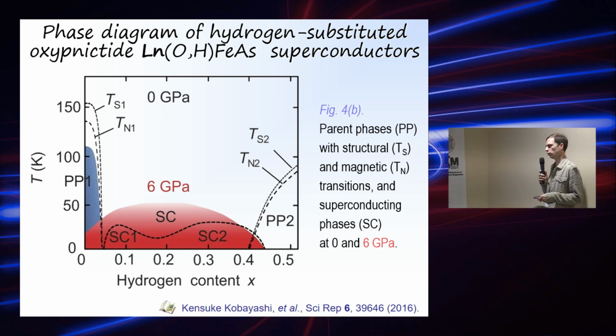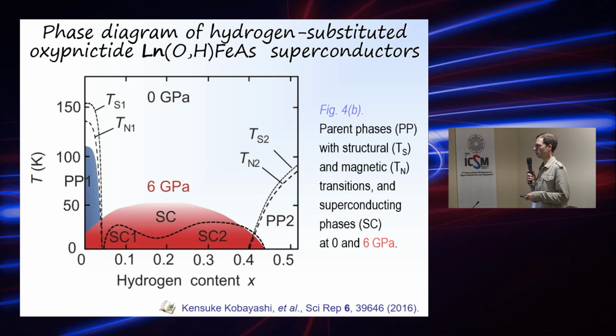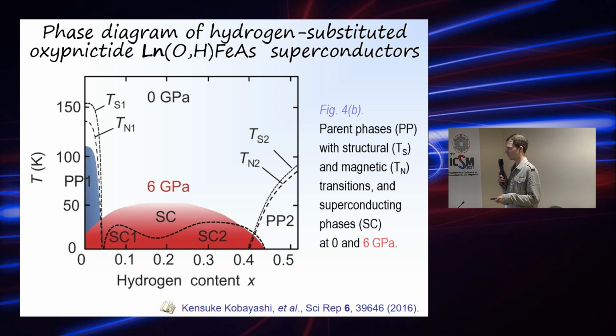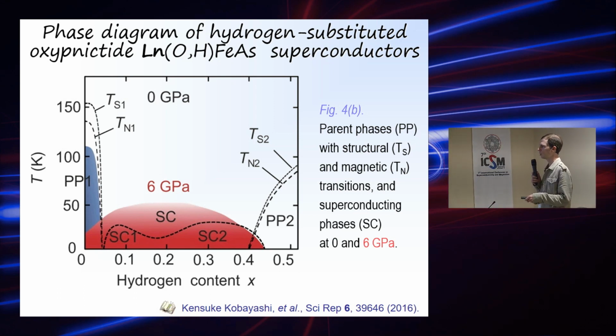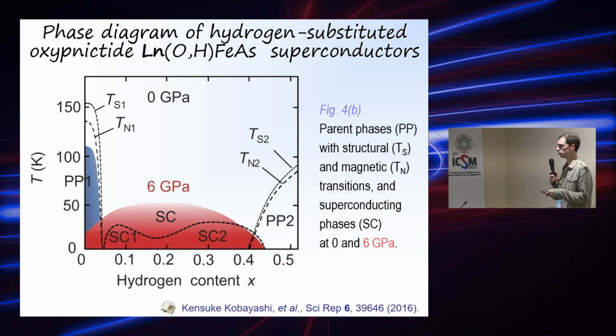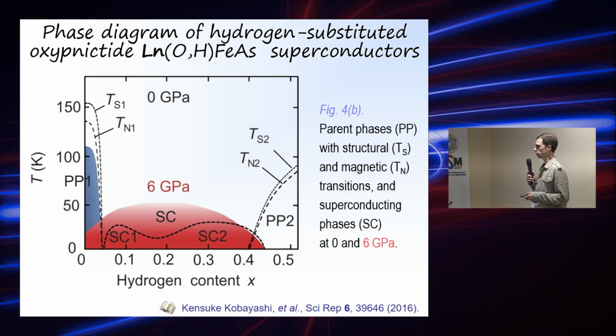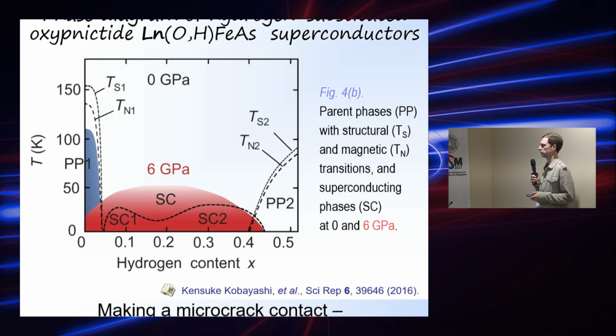From the other side, if you apply pressure, and the data for the 6 GPa pressure is presented by the colored parts, you see that this dome combines into one, and the maximal TC is nearly the same as for other 1111 compounds. But it's very unusual from this point of view.